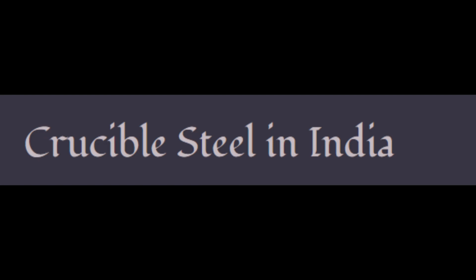This steel, generally now called wootz in the literature, but see below on naming, is a kind of crucible steel. The method of producing crucible steel, which is developed in Europe only much later, in the 18th century, begins by using fairly high quality wrought iron as feedstock, that is, iron produced in the bloomery process. So we should keep in mind that the crucible process replaces the cementation or case hardening process in turning iron into steel, not the smelting process, as compared to cast iron above. Indeed, it seems that in many cases, wootz steel was produced from a mixture of wrought and cast iron, the latter either imported from China or later produced locally.